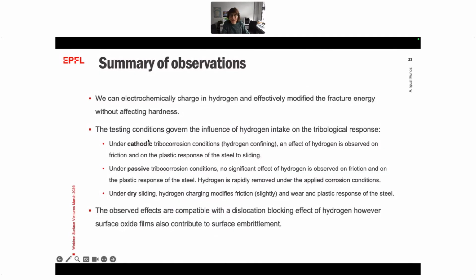And then this influence of hydrogen is really influenced by the testing conditions. When we don't have these surface films and we work under cathodic conditions, hydrogen is confined in the material, and then we see the difference in plastic response of the steel. Under passive conditions, we don't see it. There are other effects that play a role.